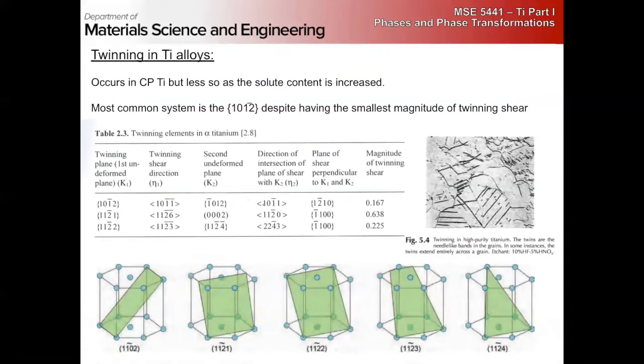Okay, so to make up for this lack of ductility, this lack of easy modes for c axis deformation in hexagonal, a lot of hexagonal metals twin like crazy, especially in pure state. So commercial purity titanium ends up with a lot of deformation twins. Alloys like Ti-6-4 do not, this generally holds across all HCP metals. Pure magnesium twins. When you look at it, AZ-31 does not. It's very, very difficult. You have to go to high strains to get AZ-31 twinning.